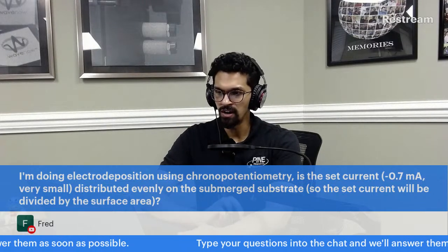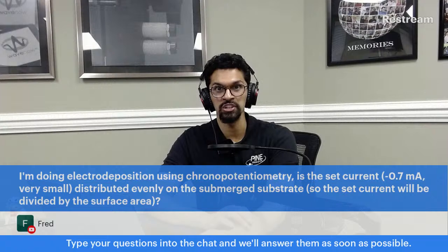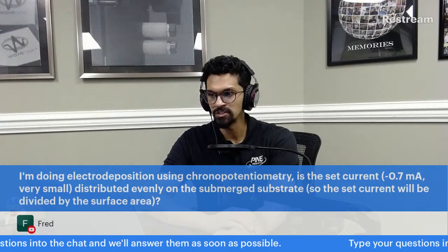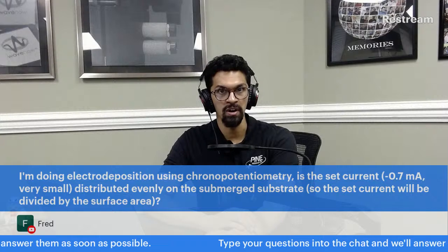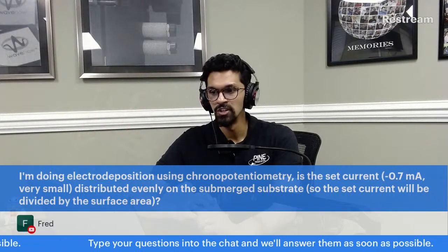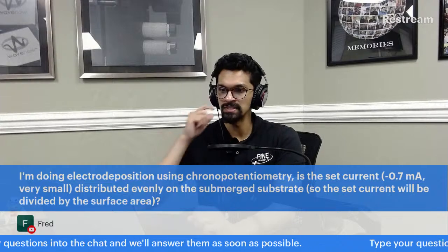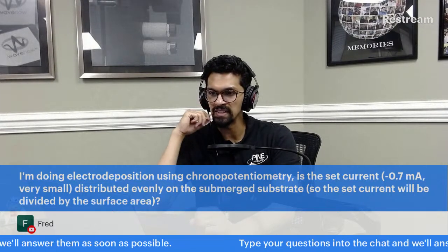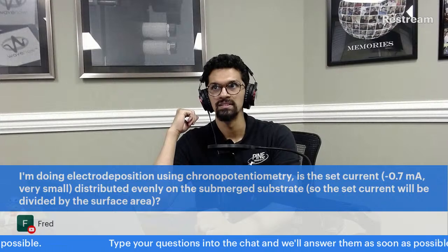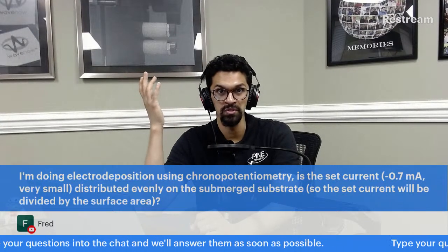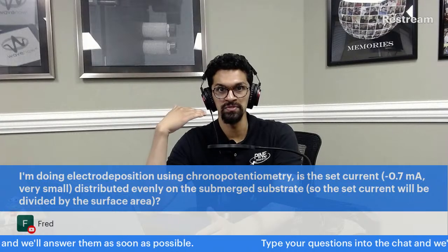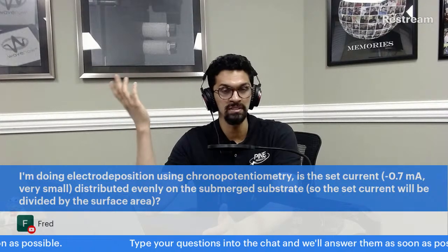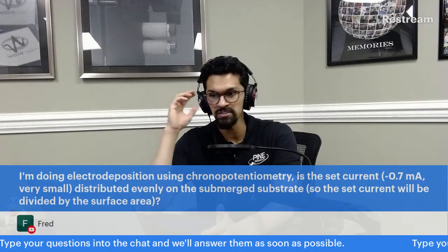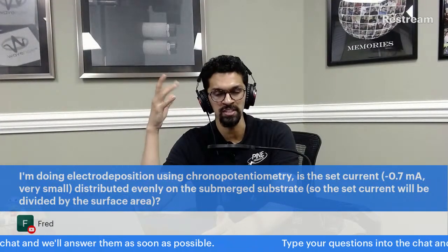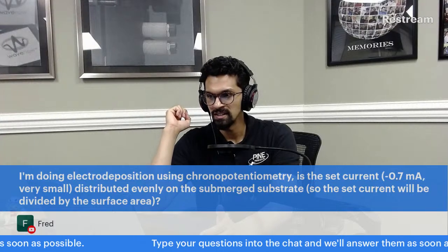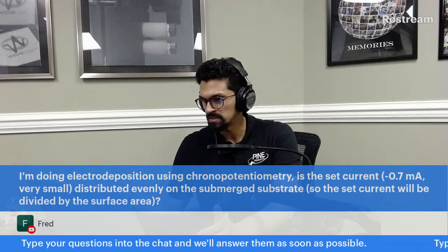Yes. If you have a big plate and you're looking at the current density, then yes, the negative 0.7 milliamps will be distributed across the entire area of the working electrode. Now, the question is, will it be distributed evenly? I think that's going to depend on your working electrode and the surface morphology of the working electrode. If it's very flat, if you have a uniform solution, if you have good stirring and good mass transport, or if you're controlling mass transport for chronopotentiometry, then yes, it will.